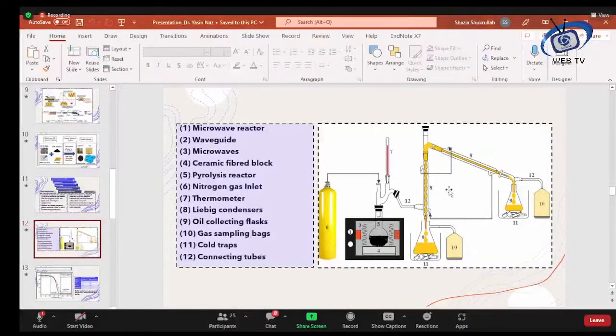So this is the schematic of the experimental setup. It consists of a microwave source. This microwave source is shielded with a pyrolysis chamber, and it has a ceramic fiber block on which we put the feedstock, and then there is a microwave guide. That waveguide focuses the microwaves onto the feedstock, and the feedstock converts into liquid, vapors, and gases. We use nitrogen as a carrier gas. This nitrogen carries the vapors and the gas towards the condensers and the cold traps, and then we collect the gas in sampling bags, and also use a gas sampler to check the composition of the gas we produce in this process.